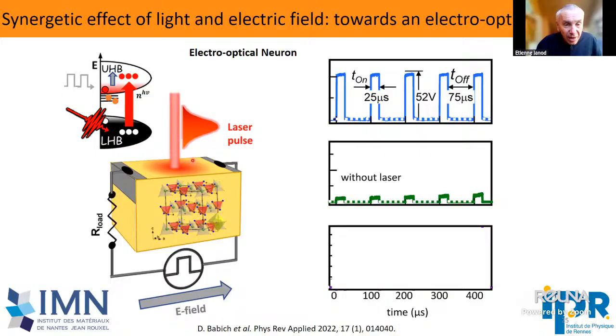So in fact, we have done an experiment where on the one hand we apply electric pulses, and also we synchronize these electric pulses with an ultra-fast light pulse, sent by a pulsed laser of duration, roughly speaking, 100 femtoseconds. So we have done an experiment which is a bit similar to the one I showed 2 slides ago. That is, we have sent electric pulses and we have chosen conditions in such a way that nothing happened. You see, we have applied 5 pulses, as you can see here.